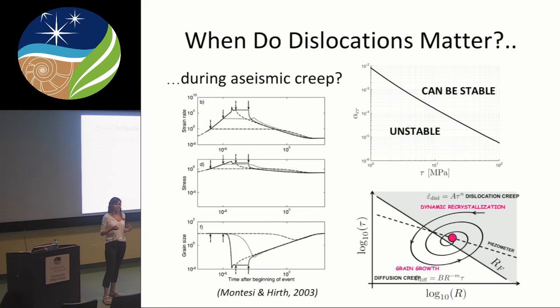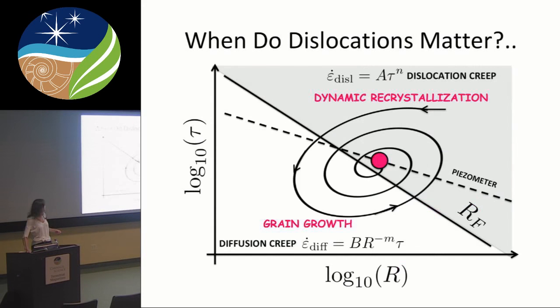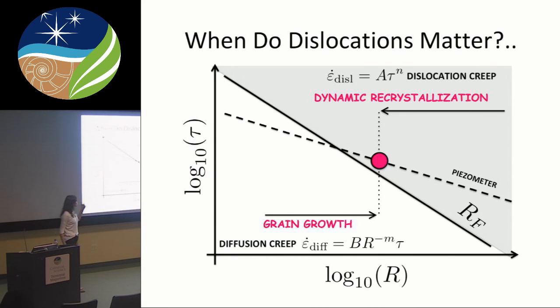But would you expect this importance of dislocation versus alpha, temperature? I would say yes, mainly because, so this mainly comes from looking at a deformation map here. So temperature would be important for the dislocations mainly because it determines which deformation mechanism your deformation is happening by. So this compliance is here, sort of that determines the strain rate and thus determines this field boundary, and these are strongly temperature dependent.